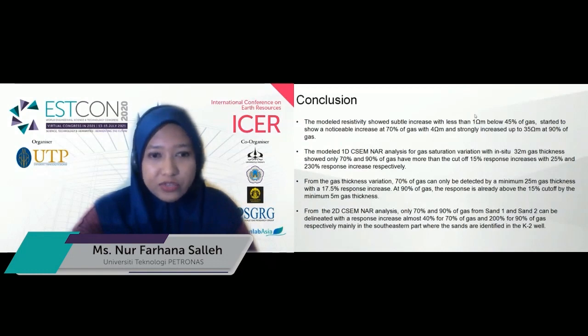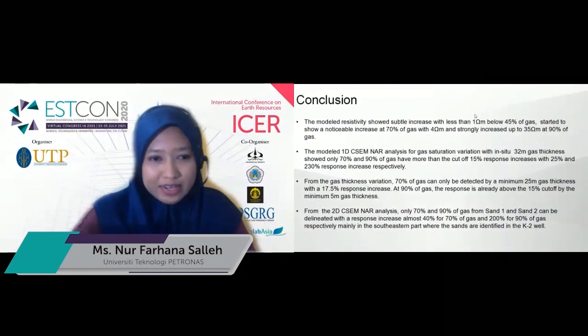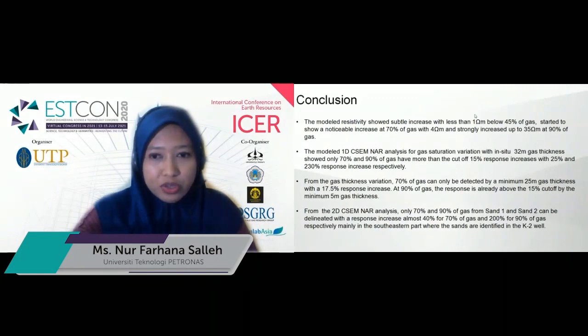From the thickness variations, 70% of gas can only be detected at a minimum 25 meter gas thickness, with 17.5% response increase. At 90% of gas, the response is already above the 15% cutoff at a minimum 5 meter gas thickness.